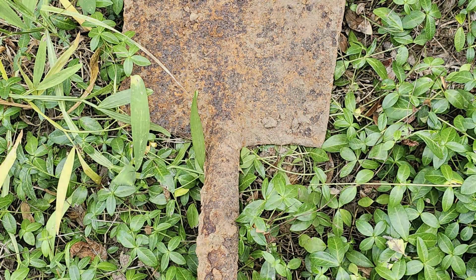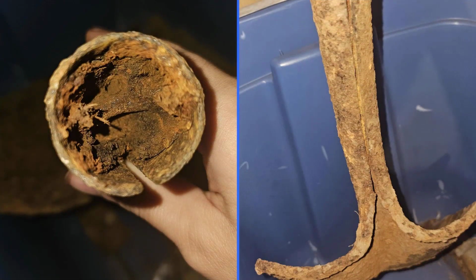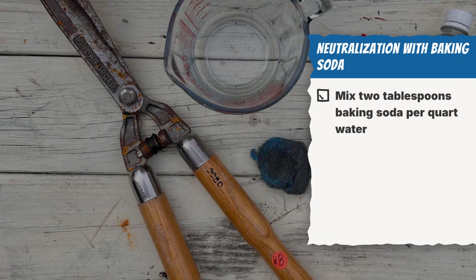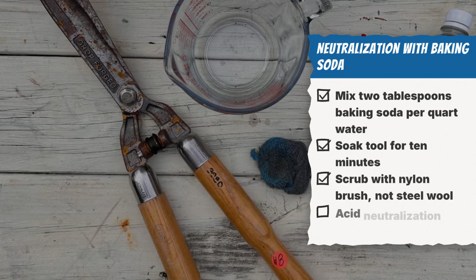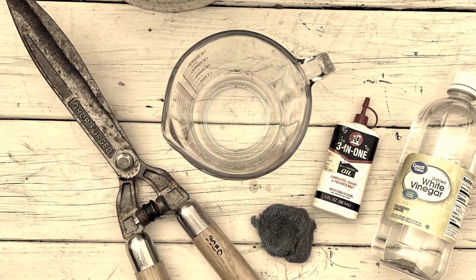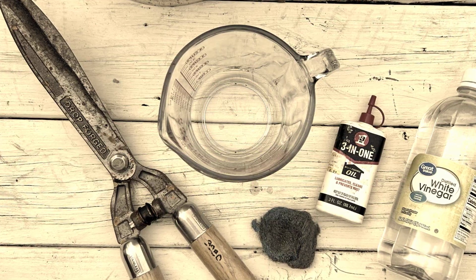The second method takes 10 minutes, and it decides whether any of the first one holds. Mix baking soda into a bucket of water, about 2 tablespoons per quart, and stir until it dissolves. Drop the tool in and leave it for 10 minutes. That solution is alkaline, and it neutralizes the acid still trapped in the surface. Skipping this is why some people find their tool covered in rust the following morning despite having oiled it. They sealed active acid under the oil.